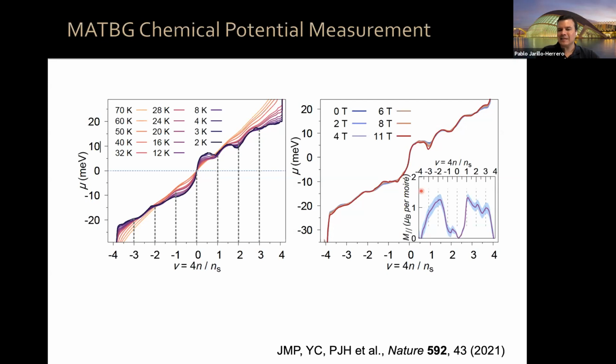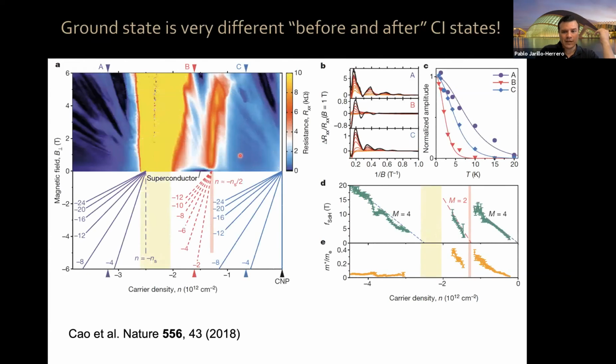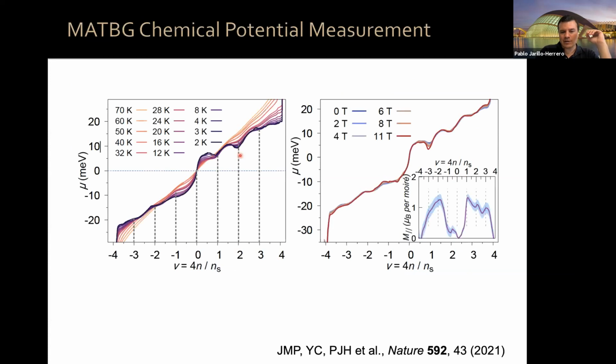But this is a technique that basically allows us to measure, in this case, the compressibility, the chemical potential as a function of density. So we can also take the derivative, dμ/dn, and we can do it as a function of temperature. So we can extract now the compressibility as a function of temperature. We can also measure the resistivity as a function of temperature. Hence, we can do the first measurement in the solid state of the electronic diffusivity as a function of temperature.